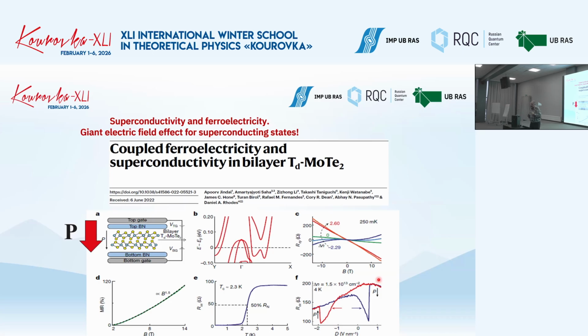And an important point is that, speaking of magnets, we know that to change the direction of the magnetic moment from up to down, we should go through some domain states. We have a lot of domain walls. The domains with wrong orientation of magnetic moment disappear as we increase the magnetic field. With proper orientation, they increase. And so you just get a change of magnetization. The same happens here. The difference is that due to this unusual mechanism of ferroelectric ordering, this change of orientation of the dipole moment is in fact associated with some change of the structure in the plane, some shifts, and this is the thing.